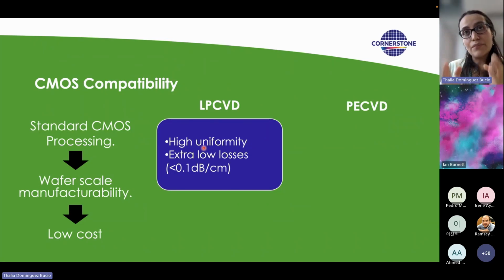Now, it's a high temperature process. What it means is that it gives us very high uniformity, and we have the potential of achieving extremely low losses, in the order of less than 0.1 dB per centimeter. In some cases, there have been demonstrations of LPCVD silicon nitride with losses down to 1 dB per meter.